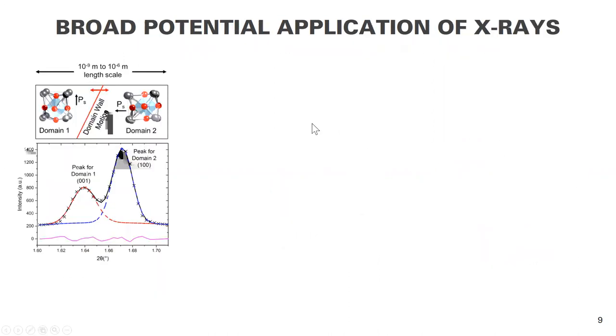So in thinking about X-rays and how X-rays can be useful in characterizing these particular effects, it's easy to see that X-ray diffraction provides a couple peaks that provide an indicator for the volume fraction of these different domain variants that you might be wanting to measure.